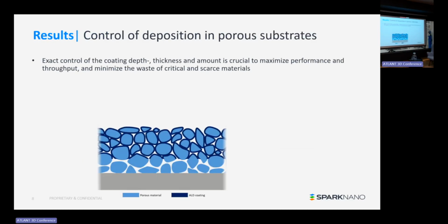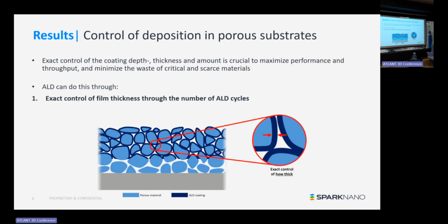So what is important in these applications and also others is that we have exact control of how deep we penetrate into the film, how much material we apply, to of course maximize the performance of the device, but also to minimize waste of critical and scarce materials. I mentioned iridium and platinum are, of course, expensive materials. So, of course, ALD can do this. We have atomic scale control of film thickness, based on ALD cycles, but also we can very accurately control how deep we go into the film. Sometimes we need to go all the way down, sometimes we need to be halfway, sometimes we need to stay at the top, but we can control this in an ALD process.